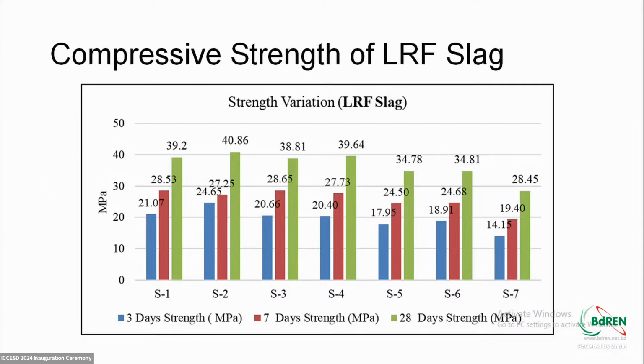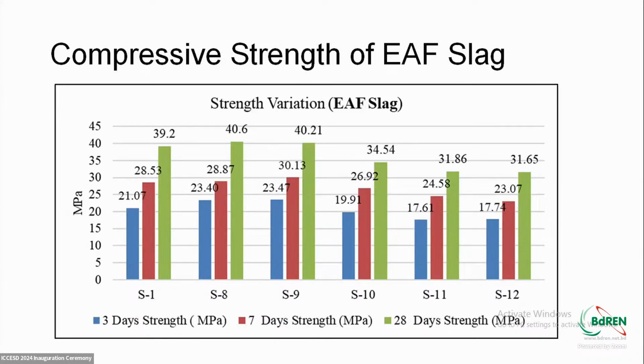In terms of strength, we find that with higher percentage of slag, strength actually decreases, but we can achieve comparable strength with OPC with up to say 15% replacement of LRF slag. In case of EAF, again, strength is comparable, but it decreases much more with higher amount of EAF slag. So both LRF and EAF slag can be used as replacement of clinker without adversely affecting the cement properties, but LRF slag is much more chemically similar to clinker.